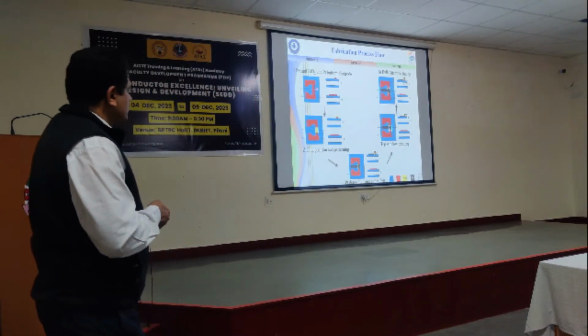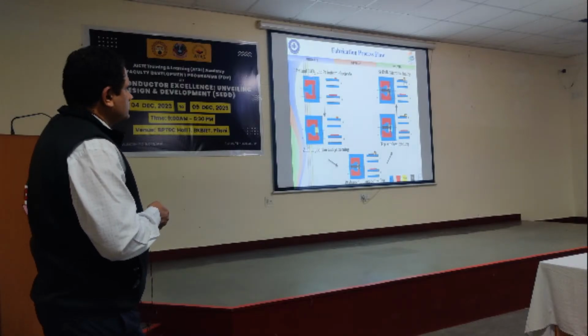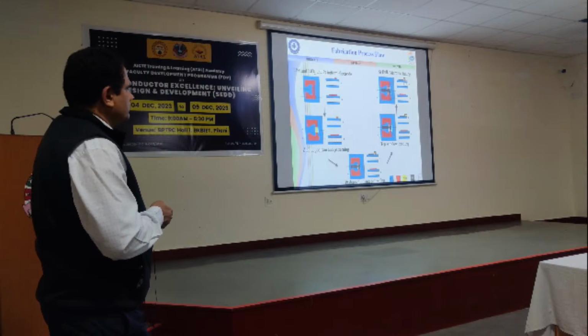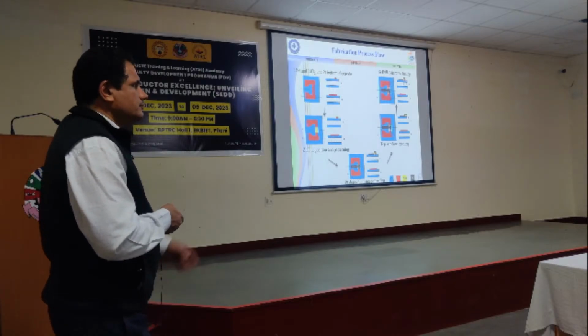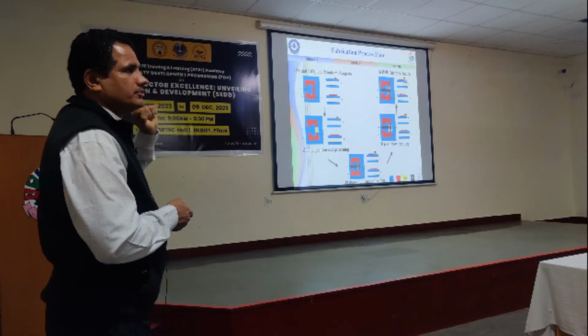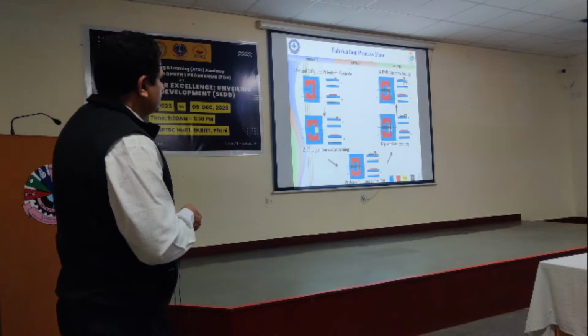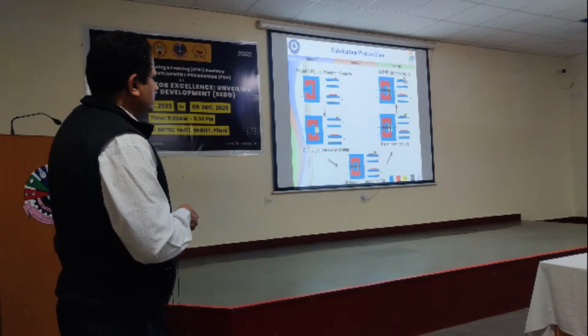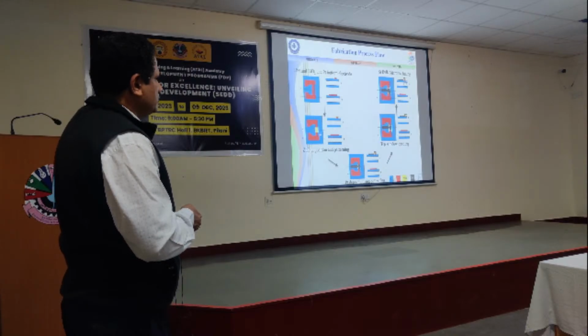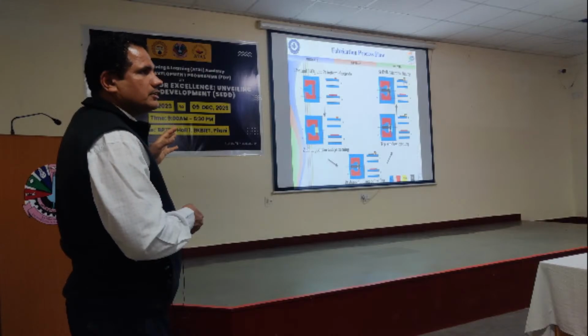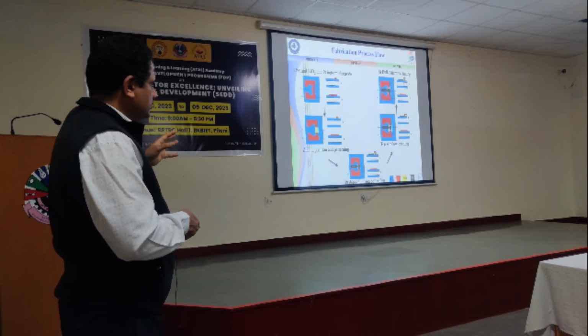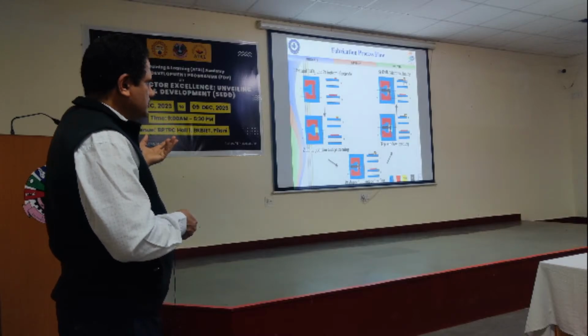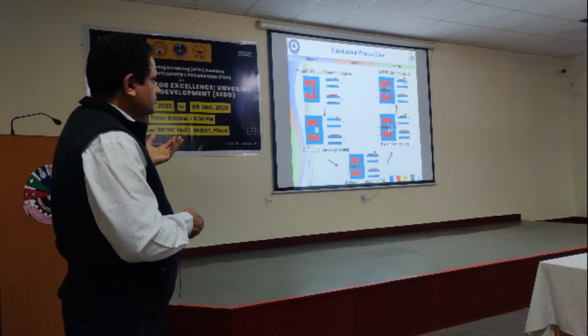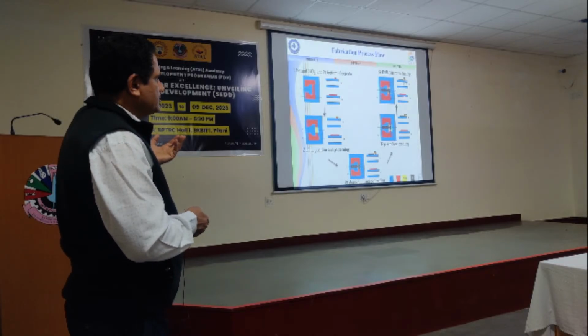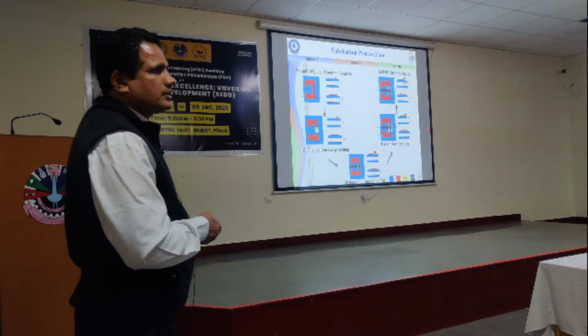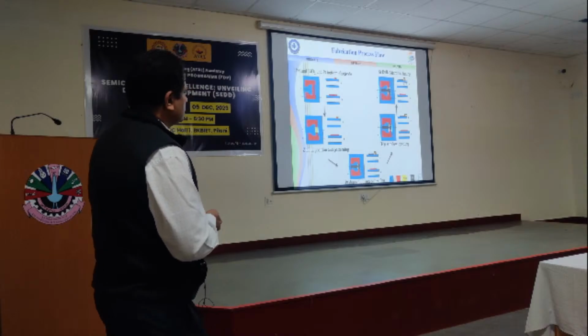See here, we start with the silicon wafers and we do the thermal oxidation of silicon dioxide, then the patterning of these platinum electrodes. On a single wafer there will be more than 300 devices. Then the second step comes, the piezoelectric layer deposition. You see here, this layer is deposited and we do the patterning using a photolithography process, a standard semiconductor process. Then the next step comes, platinum layer is again deposited and the circuit is made like this. Then comes the release of it, then comes the backside etching of it. So these are the processes we regularly do to develop these electronic resonators.